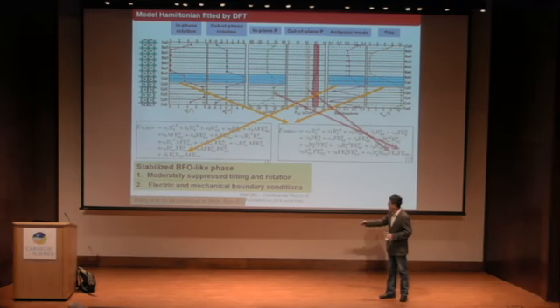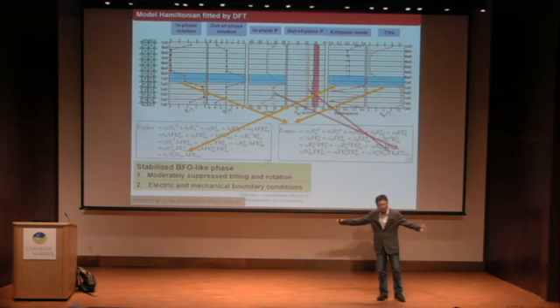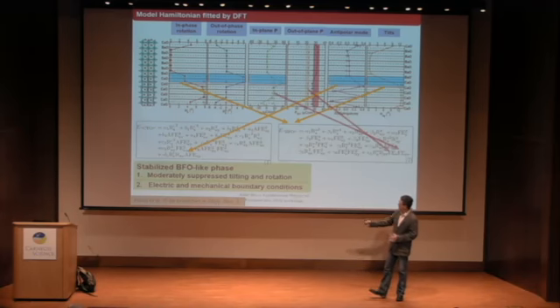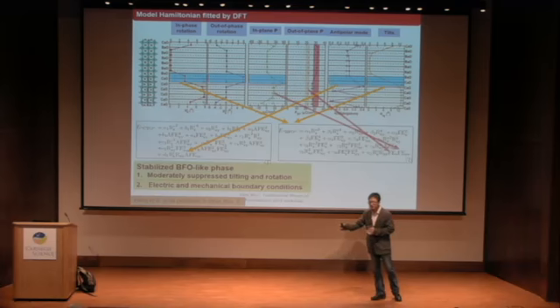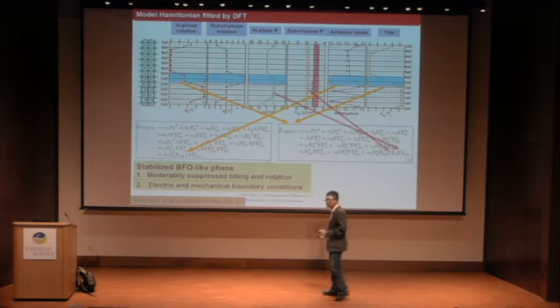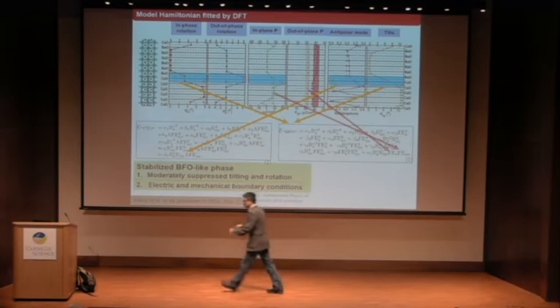So we claim that our electric and mechanical boundary conditions also help, because the mechanical boundary condition - epitaxial strain - induces a little bit of in-plane polarization, and the electric boundary conditions applied by the BTO also help push a little bit of the polarization along the z direction.